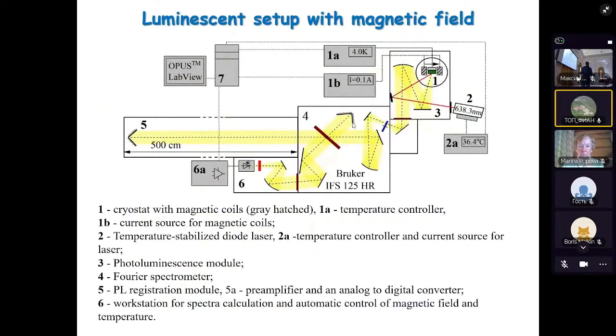So here is a scheme of our luminescence setup to investigate the luminescence in a magnetic field. We built a self-made magnetic system, which is placed into the cryostat. And also we built the module for the registration of the optical luminescence signal. And we can use different kinds of detectors to register the luminescence signal, like indium antimonide, indium gallium arsenide, silicon photomultipliers, bolometers, and so on.